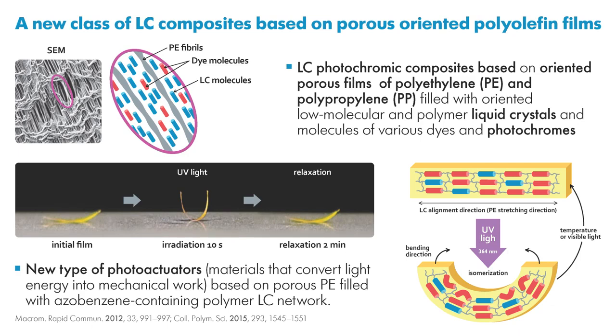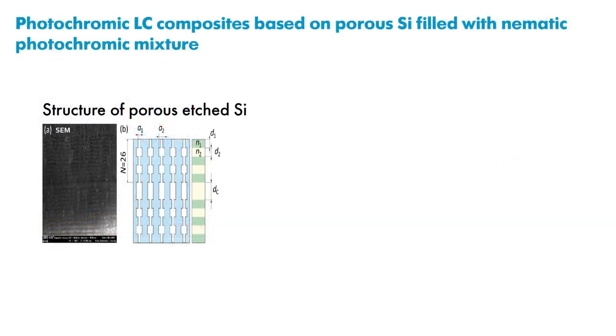As a result, bending deformation of the film takes place. These processes, isomerization and bending, are completely reversible. Another type of the photochromic composites was prepared using porous silicon filled with nematic photochromic mixture. For this purpose, a photonic one-dimensional structure was prepared from silicon wafer using electrochemical etching with controllable periodically modulated electric current.